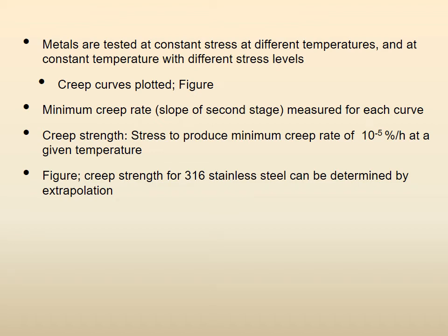We were telling you that the tests can be done at constant stress with different temperatures, and at constant temperature with different stress levels. Minimum creep rate is the slope, and the creep strength is that stress which produces a creep rate of 10 to the minus 5% per hour at a given temperature. And in the figure, creep strength for 316 stainless steel, a very common and popular stainless steel, can be determined by extrapolation. So let us look at the figures.